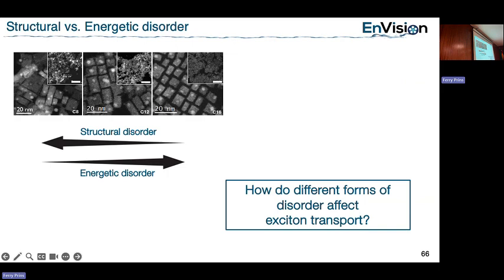Of course, how curved your particle is typically induces more defects. So people say if you have a larger surface area, then you also have maybe more defects in your particle. What we actually see is that the quantum yield goes up going to smaller particles. That means these have fewer defects than the larger ones, which again does not fit with the more subdiffusive behavior we are observing here.